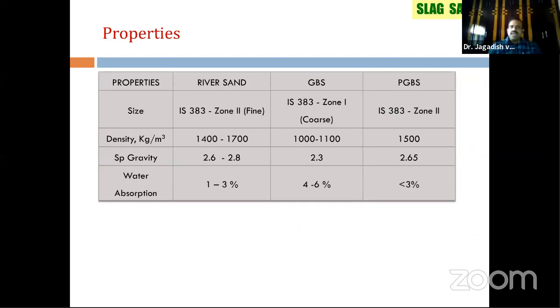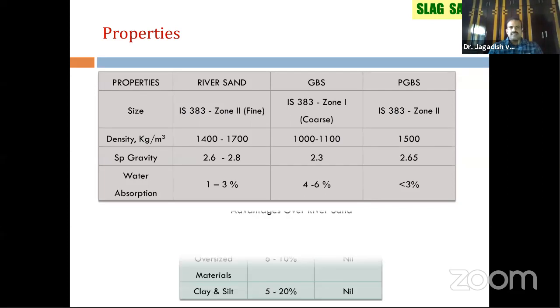So when you look into the properties after the processing, the density is almost 1500 kg per cubic meter after process. And even the specific gravity is almost like 2.65, and water absorption is less than 3%, as the pores reduced and vesicular structure is minimized, so that you got the processed granulated blast furnace slag. The properties are equivalent to the river sand.